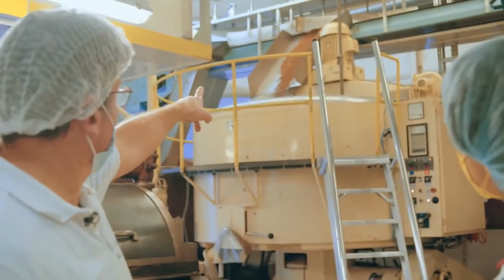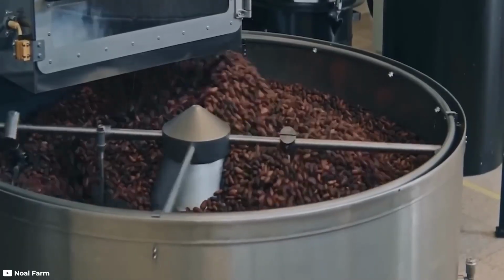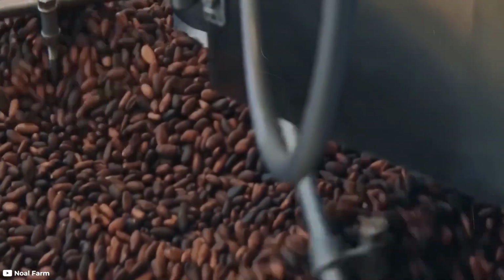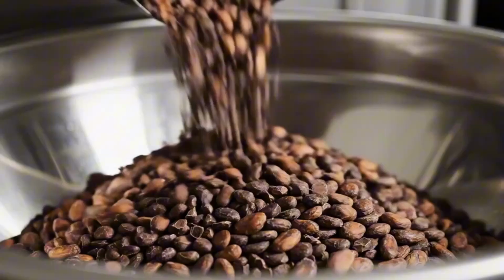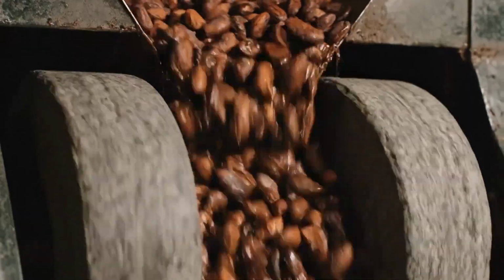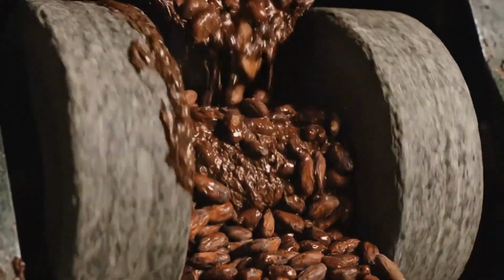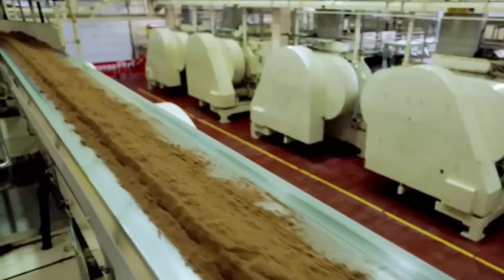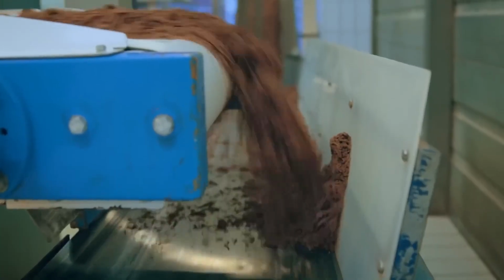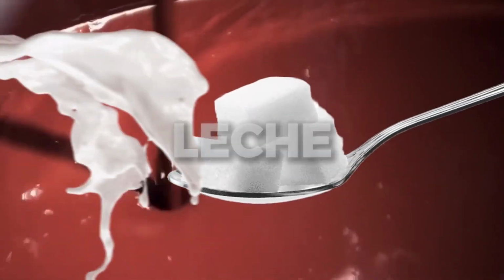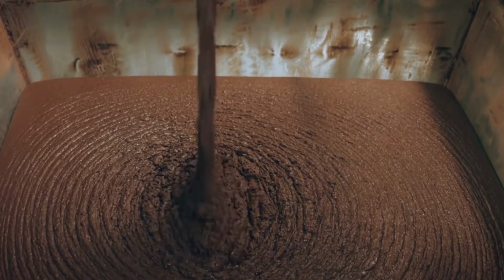What is known is that the Maillard reaction, which produces the characteristic roasted chocolate aroma, begins above 105 degrees Celsius and accelerates sharply above 130 degrees. At 155 degrees Celsius, the same reaction begins to generate bitter off notes. The roaster therefore operates in a window of approximately 25 degrees. A deviation of even 5 degrees Celsius across a batch, caused by an uneven bean load or a calibration drift, shifts the flavor profile measurably. Each roasted batch is sampled and evaluated against a reference standard before it advances to grinding.